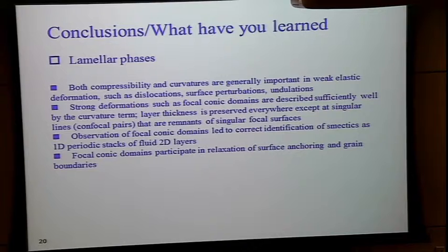You can find, for example, if you have a smectic on the substrate and the layers want to be parallel to this substrate, then it turns out that a very small distortion, let's say 1 millimeter wide, would create distortions of layers in the vertical direction that expand over astronomically large distances. In this case, 1 millimeter might cause you something like 100 meters of feeling of the presence of this little thing. So it's an interesting result of elasticity of smectics. Any questions?